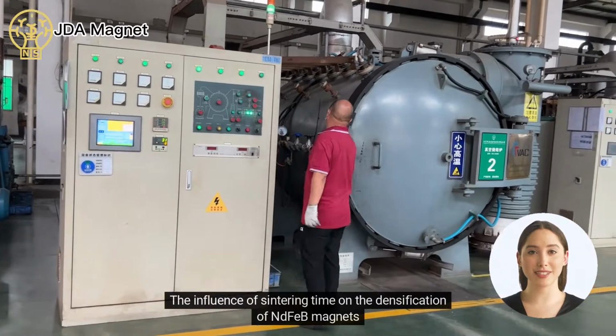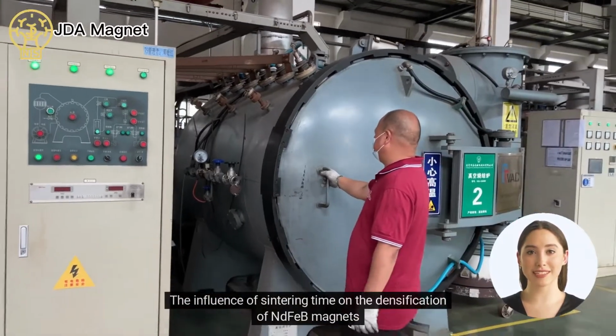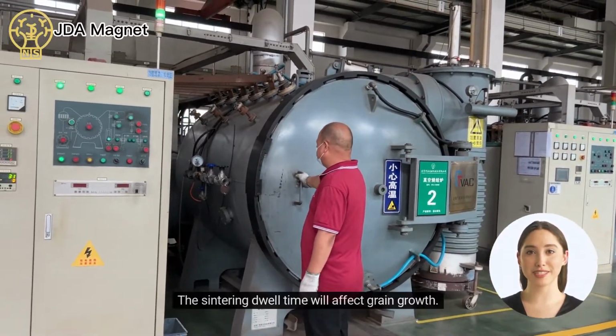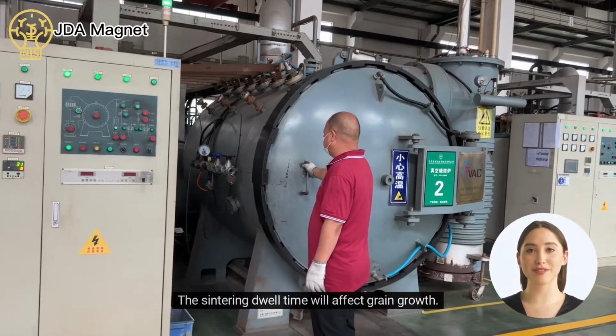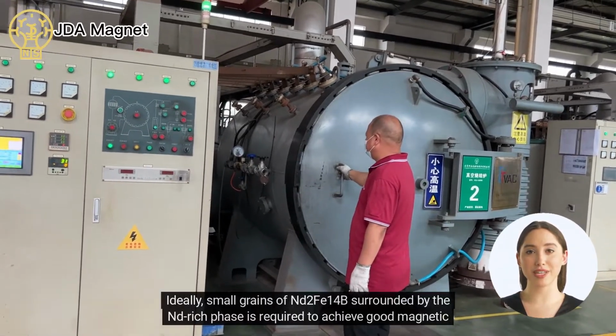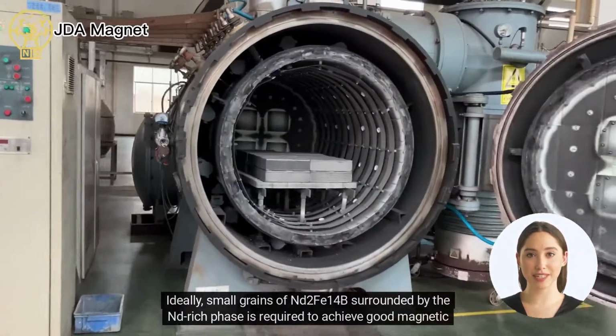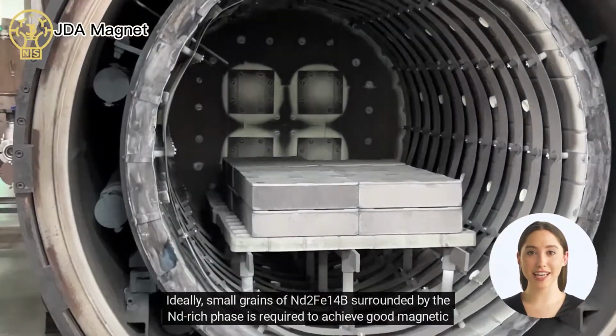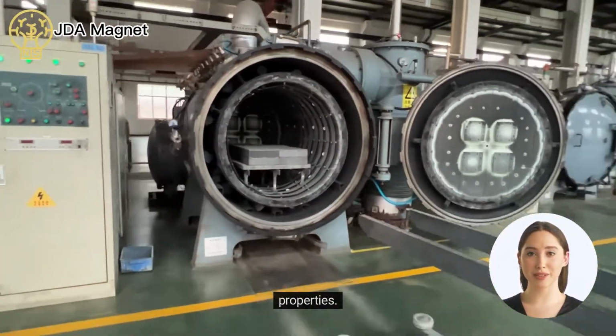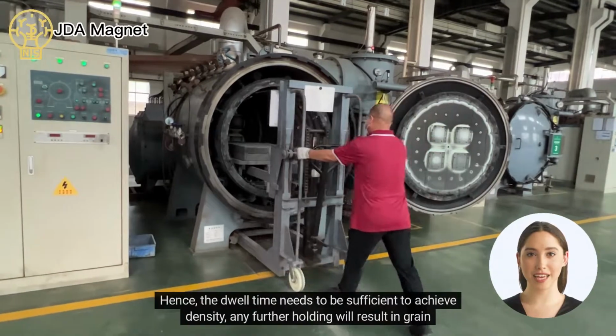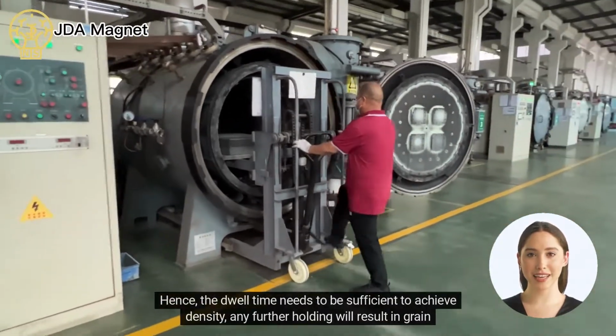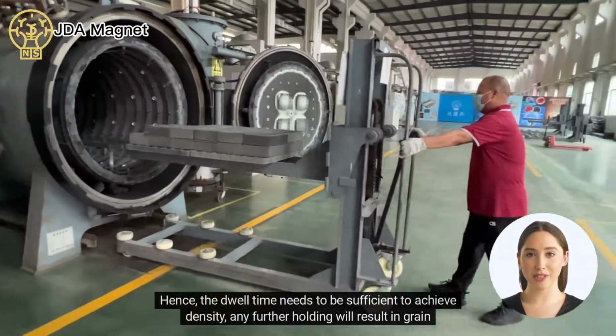The influence of sintering time on the densification of NdFeB magnets. The sintering dwell time will affect grain growth. Ideally, small grains of Nd2Fe14B surrounded by the Nd-rich phase is required to achieve good magnetic properties. Hence, the dwell time needs to be sufficient to achieve density. Any further holding will result in grain growth.